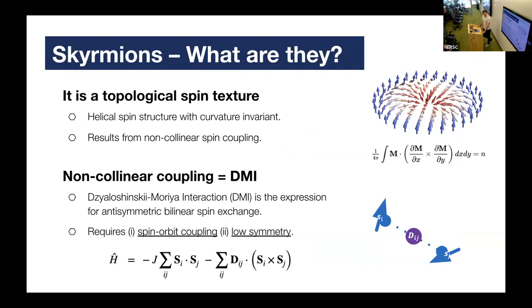So I'm going to try and run really fast here just to get to the neat part. Just very quick on what a skyrmion is. So on the far right side, you see a very cool picture, which would be showing the magnetic spin structure on a surface of what a skyrmion is. There's a few different variants of it. But the premise is that it is this non-collinear spin structure. So they're not aligned perfectly like a ferromagnet. They're not anti-aligned like an antiferromagnet. They have this interesting vortex pattern. And so the thing that makes it fascinating and makes it something that we'd actually ascribe a word to calling it a skyrmion, like a quasi particle, is because there is some invariant quantity that we can compute. So the integral expression is saying if we were to actually compute that integration on the surface, there is some fixed integral number, which is usually called the invariant that's associated with the skyrmion.